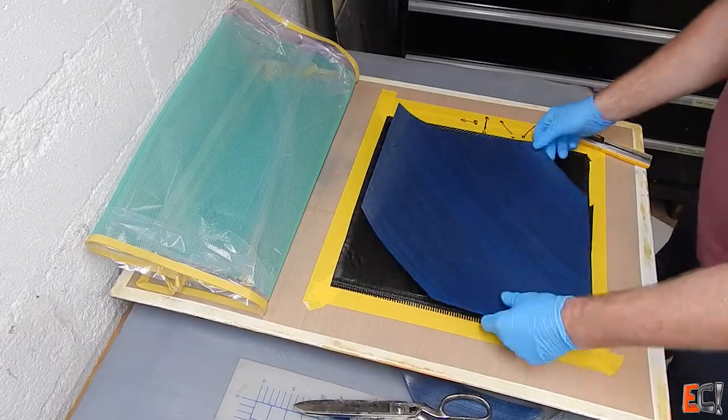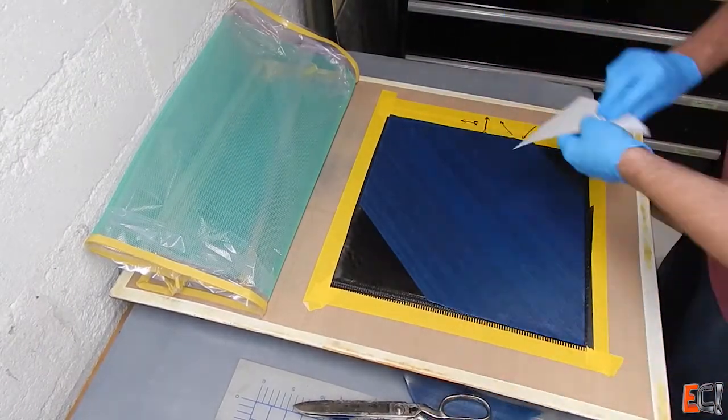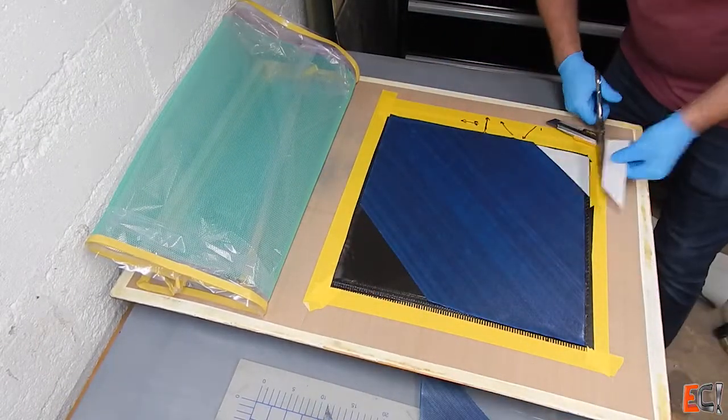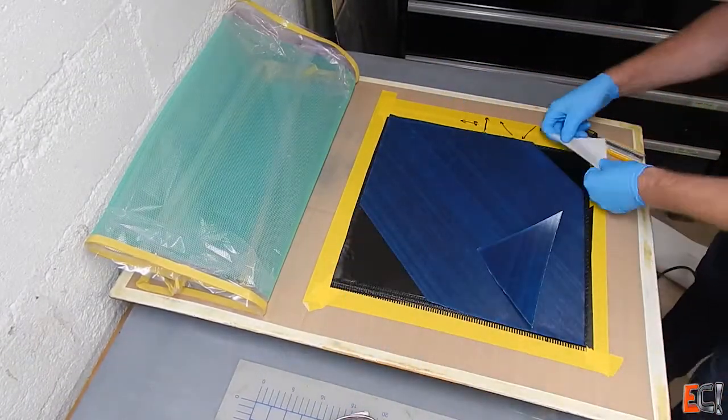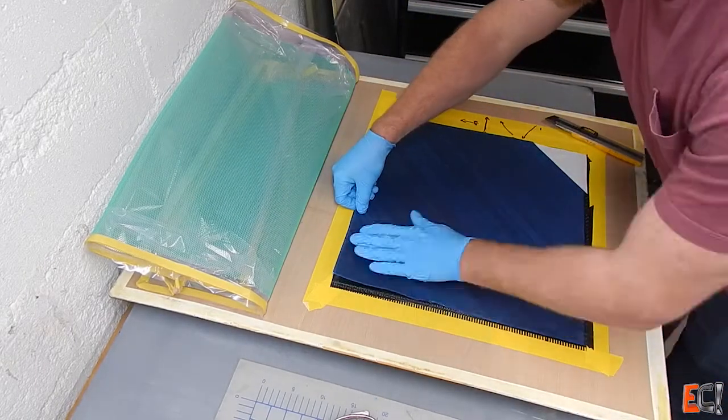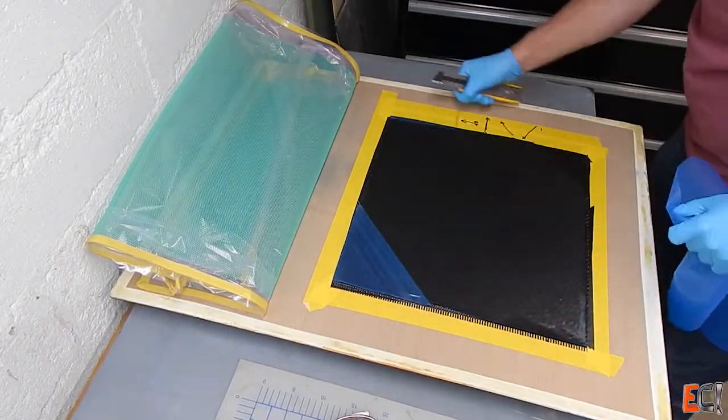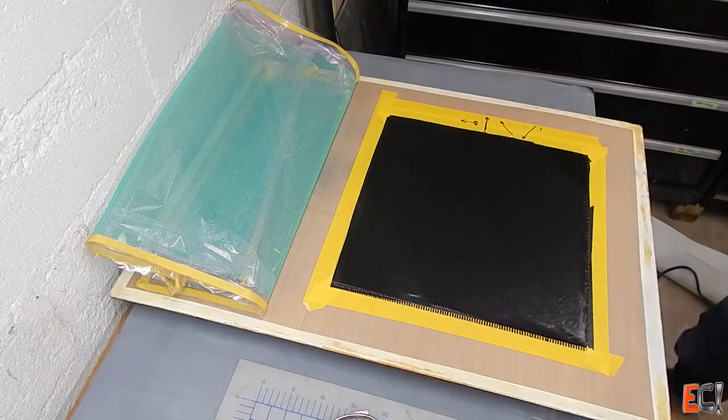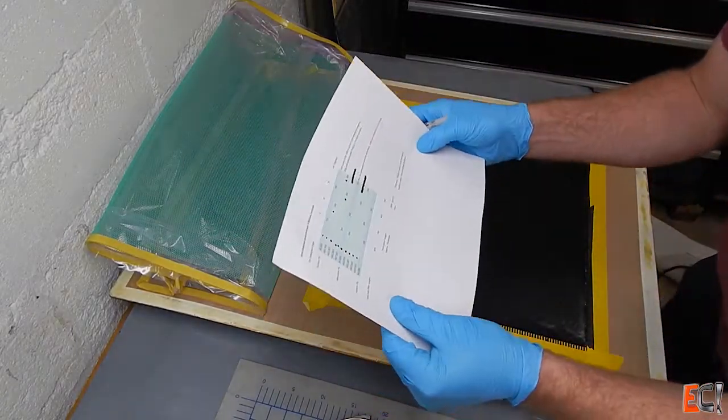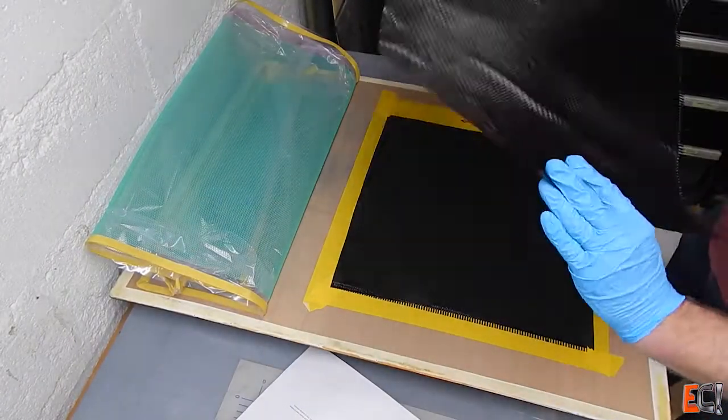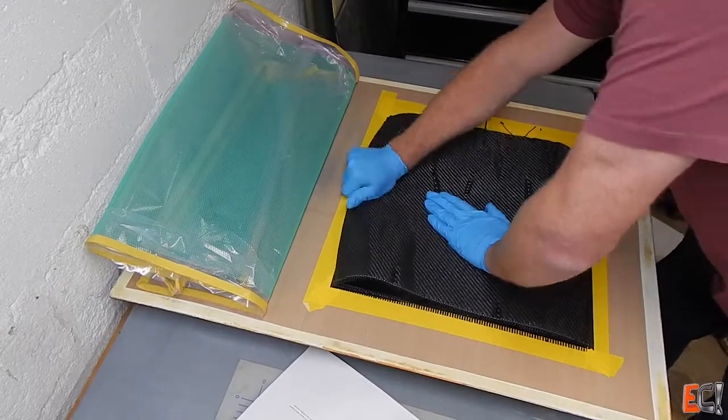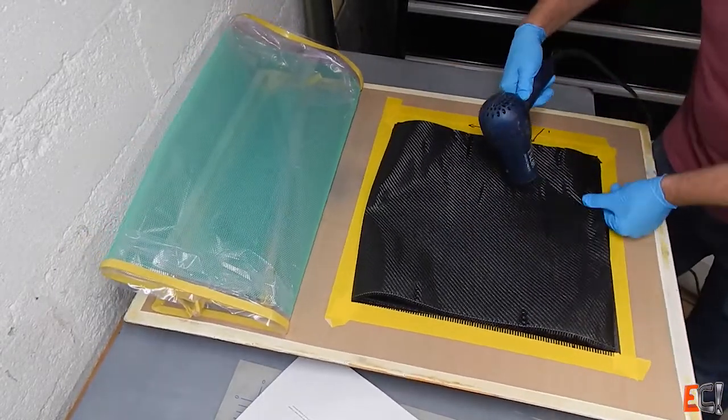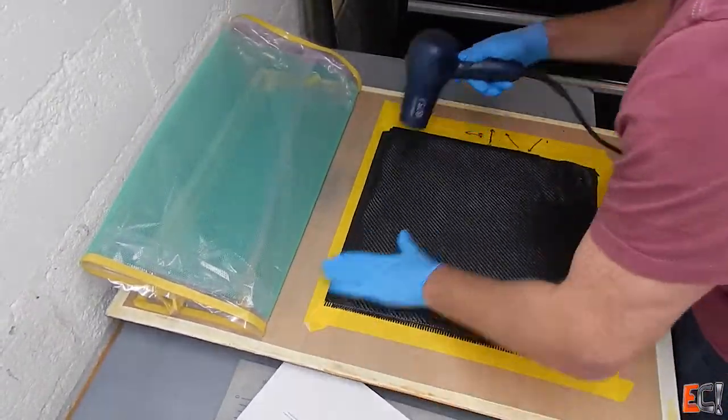As you build thicker plates it becomes more important and as there are more potential stresses built up during curing you also work towards a tighter ratio with your plies more evenly distributed. And I'm using a heat gun on this piece to put it down and work out all the wrinkles.